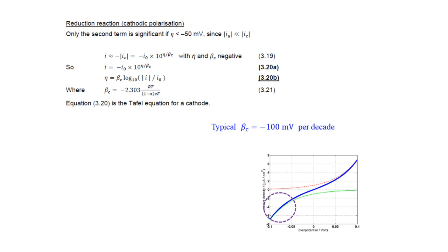Likewise, the Tafel equation for the cathodic process, or just the reduction process: if I have a polarization more negative than minus 50 millivolts, then in equation 3.19 my net current density is approximately equal to just the reverse process. It's cathodic, so I say it's a negative quantity. And I pull out equivalent terms so that in equation 3.20a, the Tafel equation for a cathode, my net current density is a negative amount, and it's the exchange current density times 10 raised to the power of polarization over beta cathode, where beta cathode, the cathode Tafel slope, is given by equation 3.21.